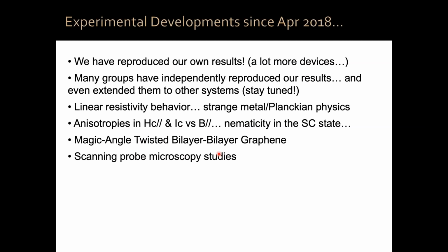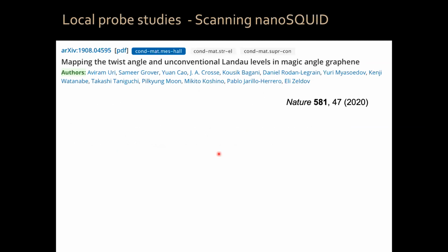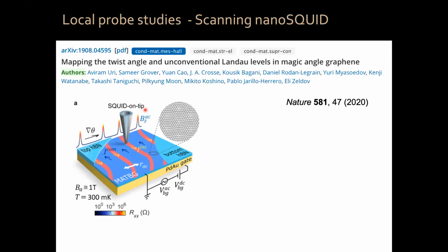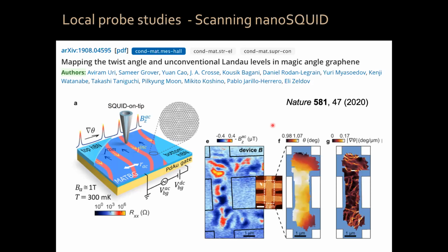I'm very happy to tell you here, and I hope Eli and Shahal will tell you about this in future talks, that I have very, very fruitful collaborations with physicists in Israel. In particular, the group of Eli Zeldov has developed an extremely sensitive technique, putting a superconducting quantum interference device on a tip that they can scan on top of our magic angle graphene devices. That tip is very sensitive to magnetic fields, so they can look locally at the twist angle in our system. We can see that in these systems the overall angle is this magic angle 1.1, but it has small angular misalignments of the order of 0.01 degrees or so in each domain. And Eli was able to map it. This was the first direct demonstration of this, and we published this very nice paper.